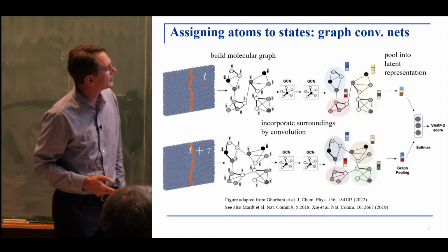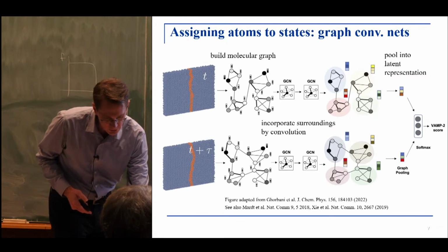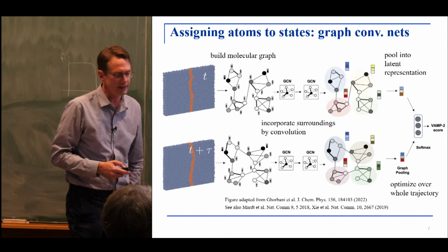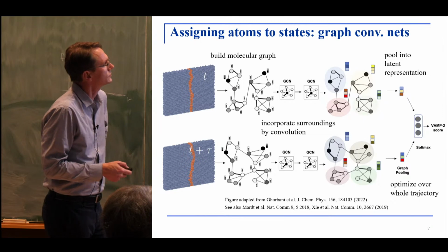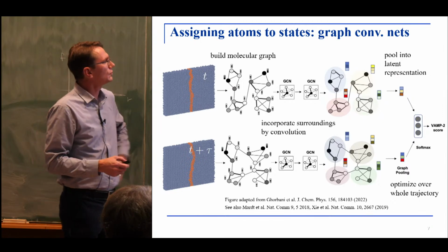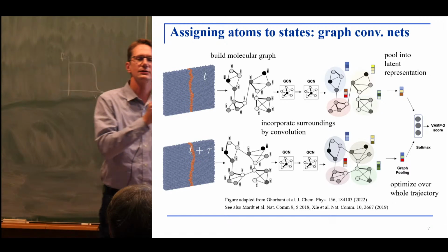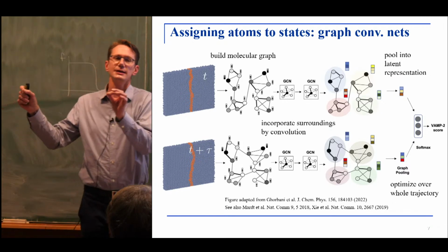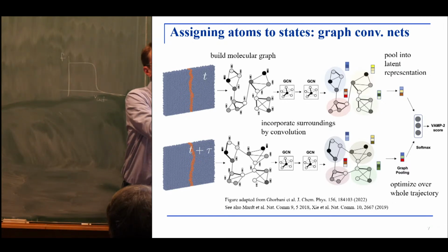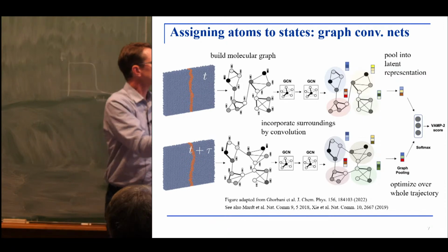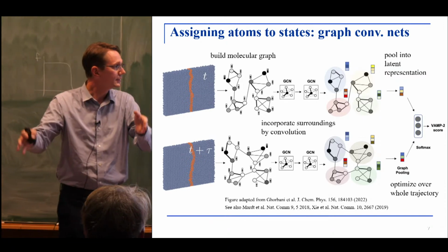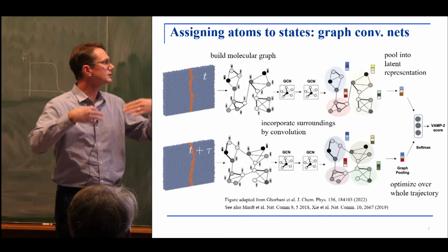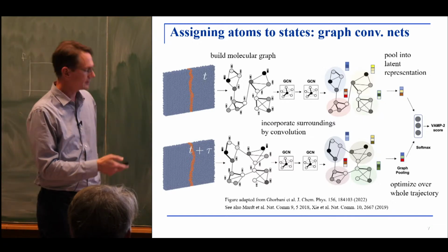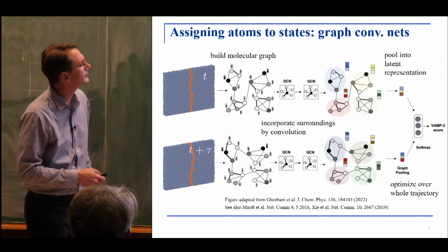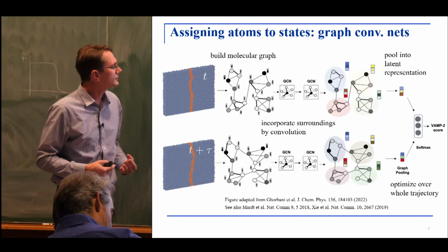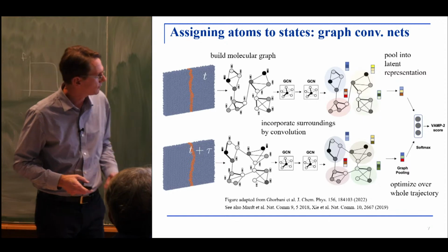And finally, one optimizes the network using this variational loss, using this variational score here. So the way this works is you obtain a molecular trajectory, and you take in the entire dynamical information of this trajectory. So you take these snapshots separated by the lag time tau, and after you've looked at that whole trajectory, you have produced this embedding here, and now you can study the properties of this system.